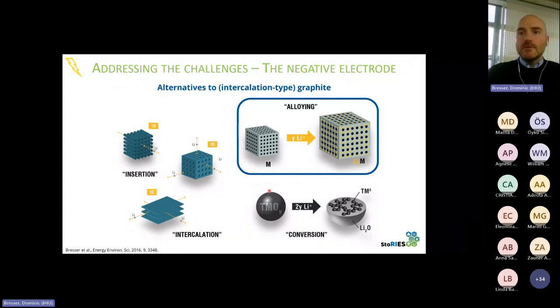We have so-called conversion type materials, which out of these three is probably the most recent one, discovered in 2000, that this process might be reversible. So commonly transition metal oxides that are then, upon reaction with lithium, basically reduced to the metallic state, so the transition metal, and then embedded in some matrix of lithium oxide.